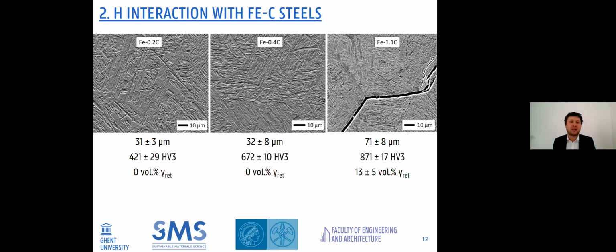And this also explains the prior austenitic grain size that was obtained. So it was quite similar for the 0.2 and 0.4 carbon steel. Around 30 microns was the prior austenitic grain size. But for the 1.1, this was about 70. And this is linked to the increased temperature during austenitization because this was needed to avoid second phases. As you can also see in the 1.1 carbon steel, we have quench cracks.